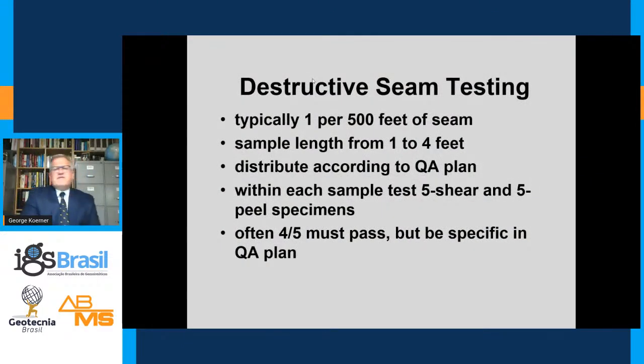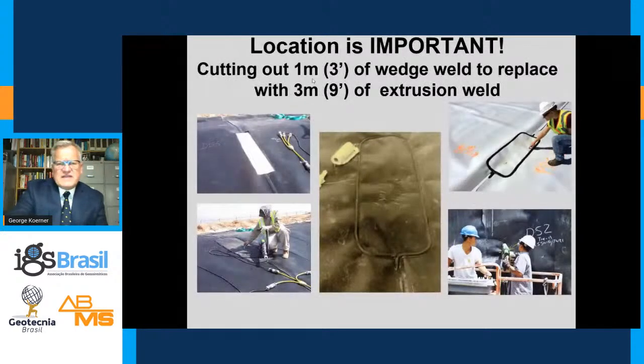This is very different than destructive seam testing, which is typically 1 in 500. We'll talk about this later in the presentation, but please realize trial seams are very different than destructive seams. The location of the destructive seam is extremely important. You will want to cooperate with the installer and put these destructive seams in above the water line or above the leachate line.